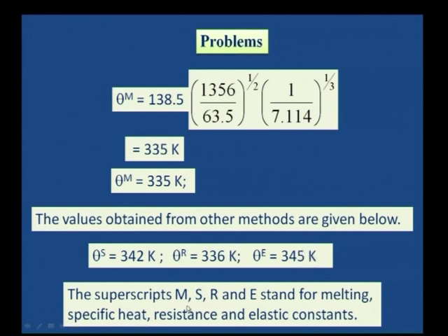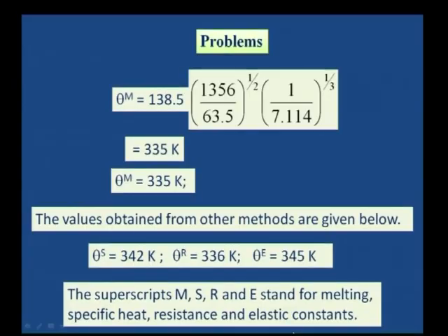So, the superscripts, as I told you, M, S, R and E, refer to melting, the specific heat, and then the resistance and elastic constants. Comments: the differences are not very much, but the important point is that this is the true Debye temperature. There are very many laws which connect properties like resistance, elastic constants, melting, all these things, to the Debye temperature. But this is the true Debye temperature, because the Debye temperature itself came into existence in the study of specific heats.